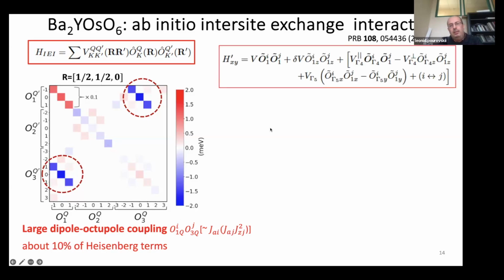So one can write this kind of effective Hamiltonian for a given bond, including only these leading couplings. And what one sees is that in result, the Hamiltonian doesn't have continuous symmetry. These octupoles, if one transforms them into cubic representations, have only cubic symmetry. And couplings for octupoles belonging to different irreducible representations within cubic symmetry are distinct and not related by any symmetry.